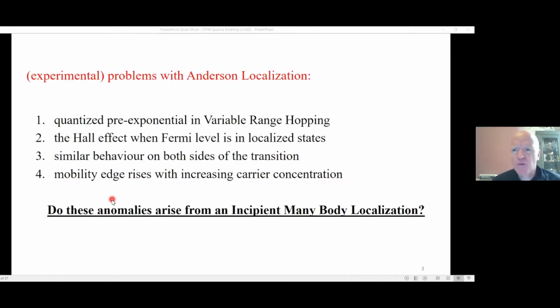So some of the experimental problems in the build up to this work, I mean, Anderson localization has been with us for 50 years or so, possibly more. And some of the experimental problems that have persisted during that period has been that when you have a variable range hopping mechanism, the high temperature pre-exponential on the conductivity or the resistivity was quantized to in resistivity h over e squared, or in conductance e squared over h. So that was always a strange phenomenon, that you've got a thermally assisted process, yet the pre-exponential was the simple quantum of conductance.